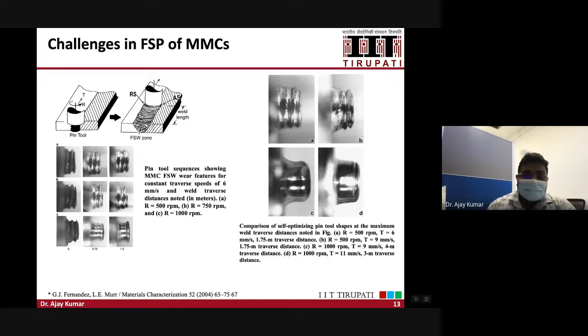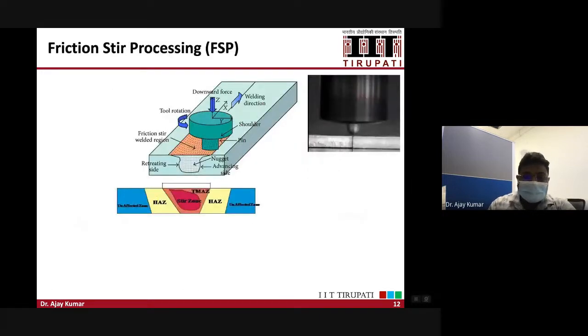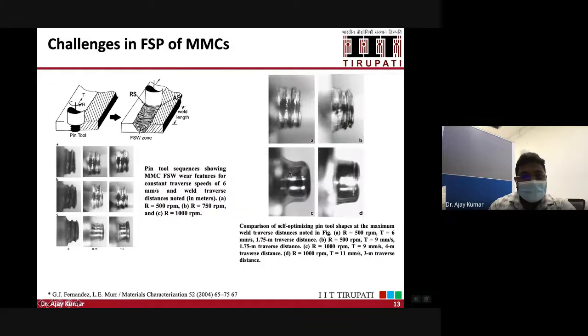So you know that in MMCs, you have the reinforcements, which are hard ceramic particles, and then you have the metal as a matrix material. But when you use this process for making composite materials, you have the FSP tool. When this tool interacts with the hard ceramic particles during the process, you will have a lot of wear, or a lot of material removal from the tool. It means that the tool is getting mixed into the metal matrix, and you will get undesirable properties. So you need to avoid this tool wear, and this is a great challenge. How will you avoid this?